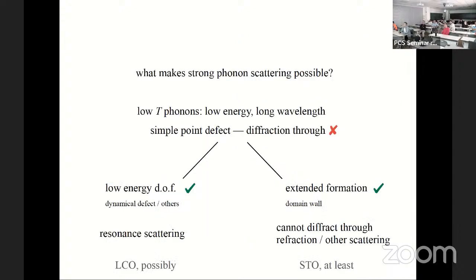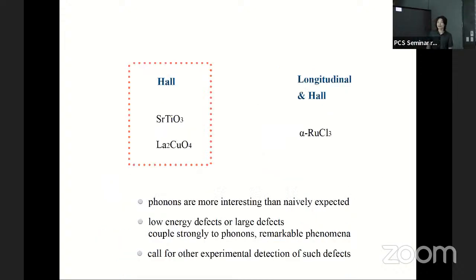Right. So overall, let's come back to this general idea. After this phenomenological study, it turns out that the study of thermal Hall effect in this insulating material comes down to what makes strong phonon scattering possible. For low temperature phonons, we need to consider either low energy degrees of freedom or extended defects. This is what we learned from this material. Since I am running out of time, I'm not sure if I should talk more about this. Seven more minutes.